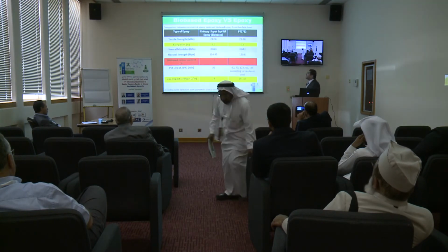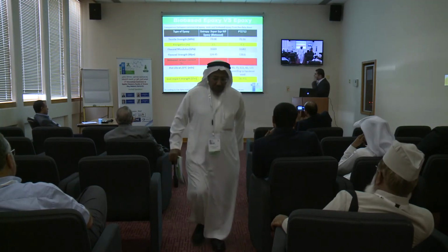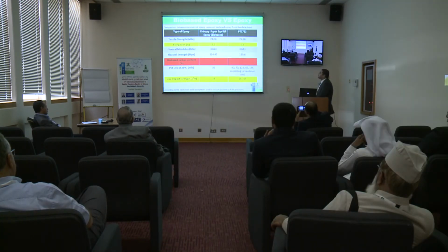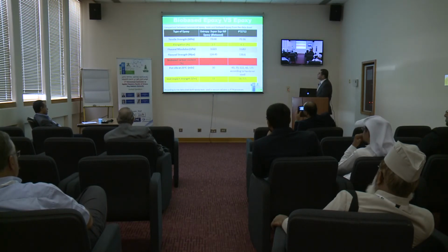After that, we tried to determine the mechanical properties of this bio-based epoxy. From the tensile strength and flexural modulus, we compared the commercial product and the new bio-based one. We found that the elongation here is a little bit smaller than the commercial product coming from petroleum resources, but the flexural modulus and strength are almost the same.